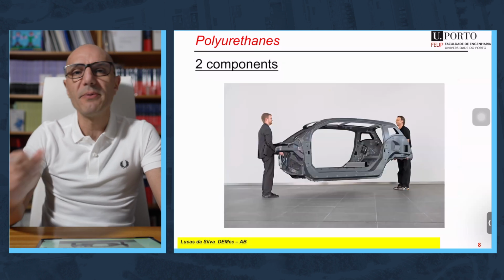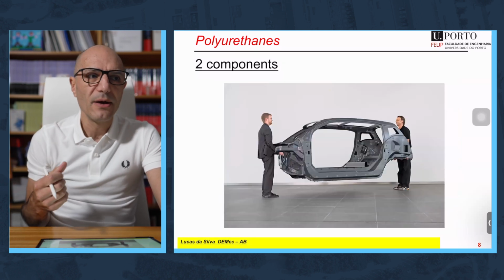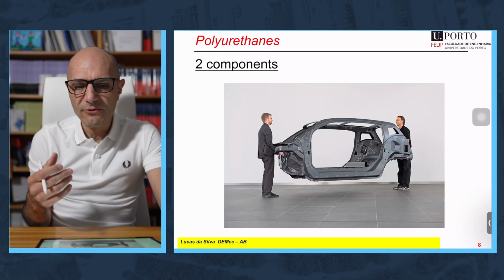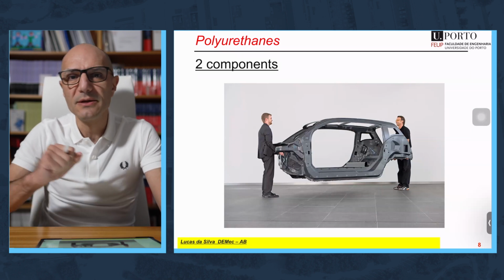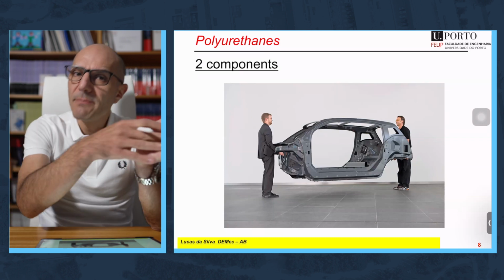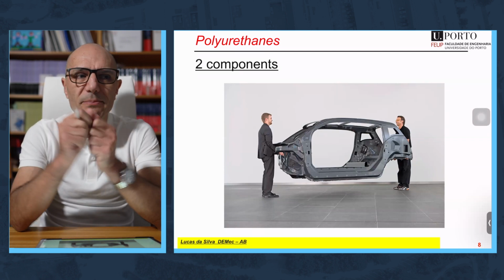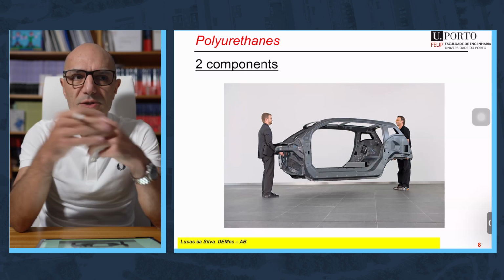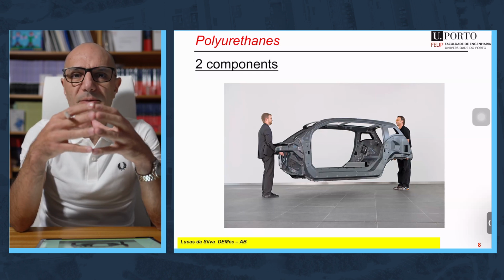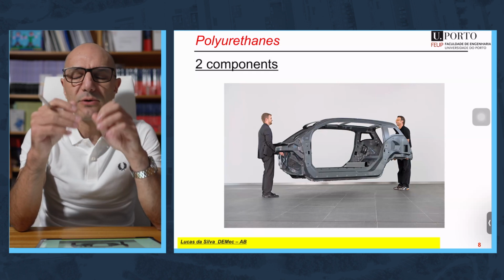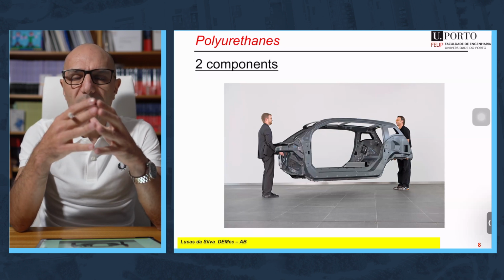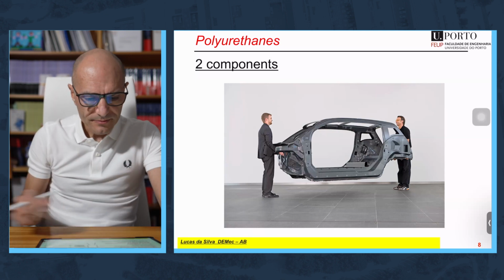weeks. The two components, they are more rigid, they are stronger, they are typically used for bonding composite materials. Better than epoxy adhesives in that case, because the epoxy adhesives are too stiff and they might cause delamination of the composite. With the two-part polyurethane, they are less stiff, they concentrate less the tension in the composite and they avoid that problem of delamination.